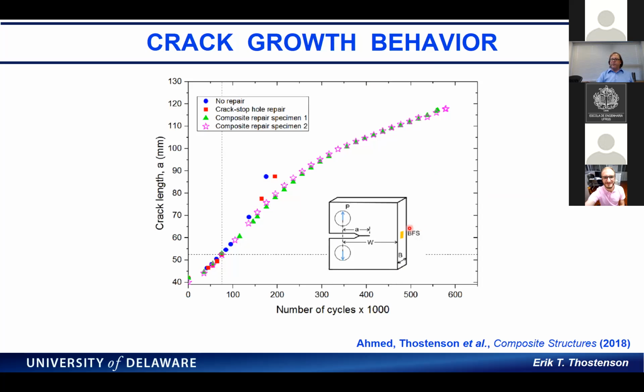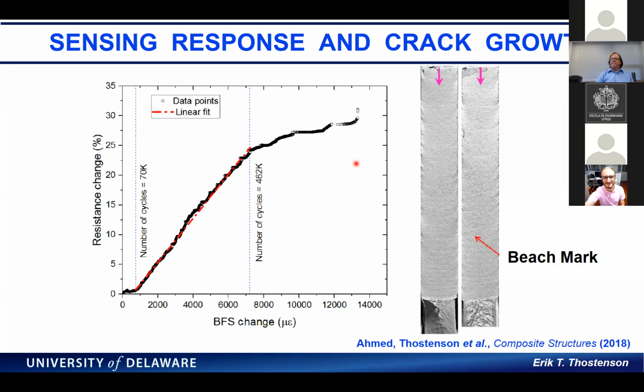One of the things we do is measure the back face strain, and the back face strain tells us something about the crack length. Here you can see that the two cases with no repair and with the crack stop repair fail at about the same crack length. But where we apply the composite repair, we can drive that crack much longer than the critical crack length because we're taking stress off of the crack tip. One of the unique things, so I'm a material scientist.